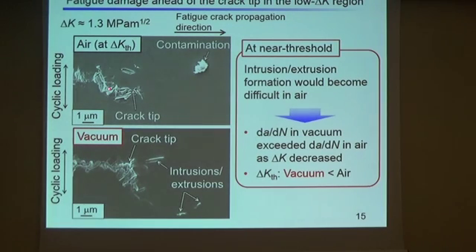For the fatigue crack in air at the fatigue threshold, intrusions and extrusions were not observed ahead of the crack tip. In contrast, in vacuum at the same delta K as the fatigue threshold in air, intrusions and extrusions were formed ahead of the crack tip, and then the fatigue crack propagated through these intrusions and extrusions. So these experimental results suggest that near threshold, intrusion and extrusion formation would be difficult in air, and therefore da/dN in vacuum exceeded da/dN in air as delta K decreased, and the delta K threshold in vacuum is smaller than that in air.